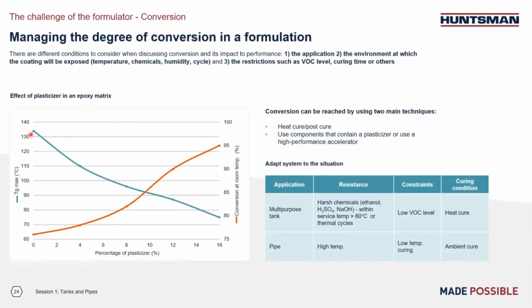So if we look at this chart, you can see without any plasticizers, this system's ultimate TG is about 135 degrees, right? But the conversion rate is only about 75%. So when we introduce the plasticizers into the system, we can improve the conversion rate, right? And all the way, if we're using 16% loading amount, we can improve conversion rate all the way to 95%, right? But at the same time, we drop the system TG to only about 75 degrees versus 135 initially, right? And so we always need to find a good balance point.